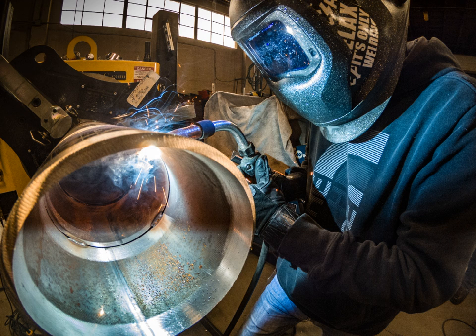The type of current used plays an important role in arc welding. Consumable electrode processes such as shielded metal arc welding and gas metal arc welding generally use direct current, but the electrode can be charged either positively or negatively. In welding, the positively charged anode will have a greater heat concentration, and as a result, changing the polarity of the electrode affects weld properties. If the electrode is positively charged, the base metal will be hotter, increasing weld penetration and welding speed. Alternatively, a negatively charged electrode results in more shallow welds.